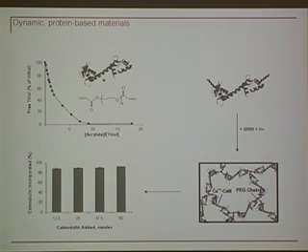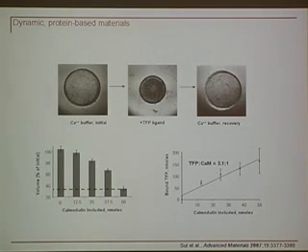So if we quantify the incorporation efficiency of Calmodulin into these gels, we get somewhere in the neighborhood of 90% incorporation, which we thought of as quite positive. And we can vary the total amount of Calmodulin present in the gel by essentially mixing the Calmodulin PEG conjugates with just PEG diacrylate units. So this potentially provides a mechanism to tailor the responsiveness of the material.